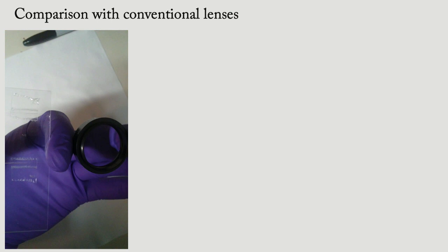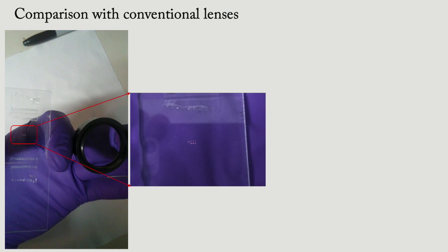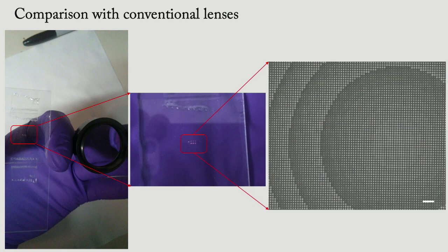Now, there's also a glass slide, and if you zoom in very closely here, you can see there are 7 dots. And each of these dots is a lens. If you focus on this dot, this is what you're going to see, a very, very small nano scatterer that we are making. So we can make extremely small lenses using this technology. This lens can have like 10 to 20 micron focal length, so a very short focal length. And more importantly, we can be really creative and create different kinds of phase profile. And as I said, we have not really done anything on the scatterer geometry, but that's another avenue that we are currently pursuing to see if we can even extend the capability of these metasurfaces.